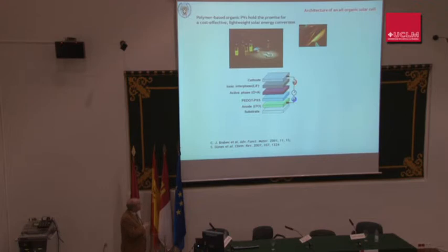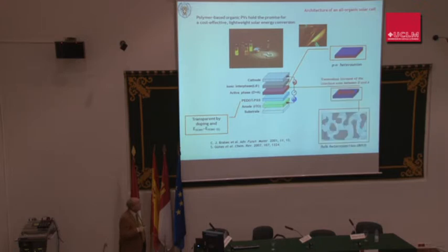Something which people don't realize is that PEDOT:PSS is not transparent. However, after doping, it becomes transparent, so for our purposes it is quite good. Also, initially in a PN heterojunction, the donor and acceptor are together, but the interaction only occurs at the interface. This is important because for many years the so-called bulk heterojunction concept was handled. This concept was developed in the first European project funded by the European Union, with 10 groups at that time, in the middle 90s, and our group was already participating in this project.